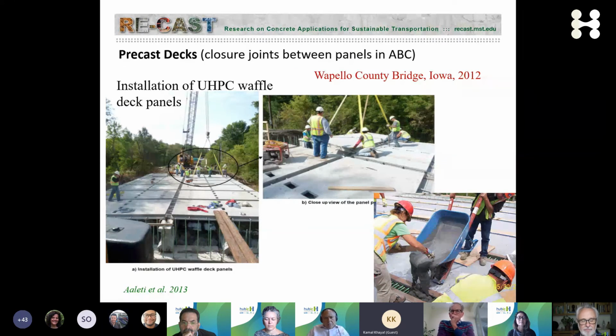In the US, we've been having a lot of automation in construction, if you would, where a lot of the fabrication of bridges is taking place in manufacturing plants, and sometimes even on site, and they're pushed in place. This trend is called accelerated bridge construction. In this case, you have bridge deck elements that are prefabricated and placed together and then bonded together using UHPC in these sections. As you can see, UHPC is highly flowable, but very, very viscous.